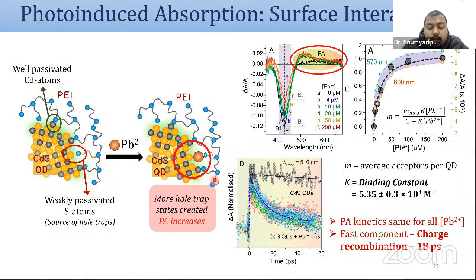Why not mercury? There are other reports where they showed PEI has a different kind of mechanism to bind well with mercury as well. Basically, when you put different cations, they do not have access to the quantum dot surface due to the coverage of the PEI, and the PEI catches the cations and restricts their access to the quantum dot surface. But lead-2 plus does not bind with PEI, so it goes directly to the surface, and